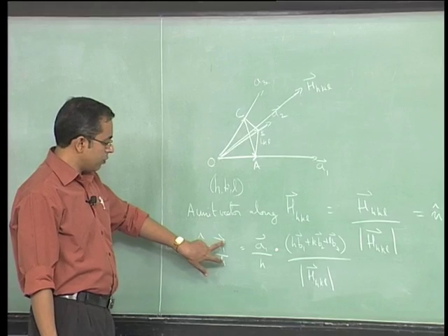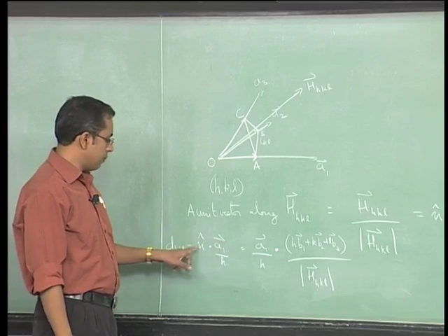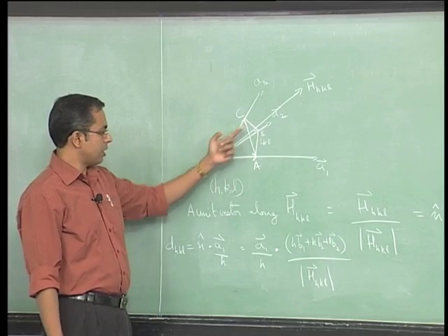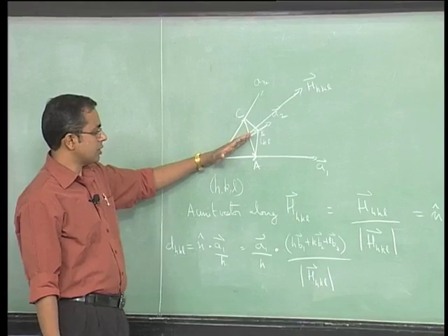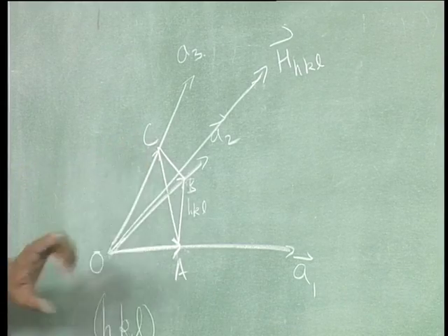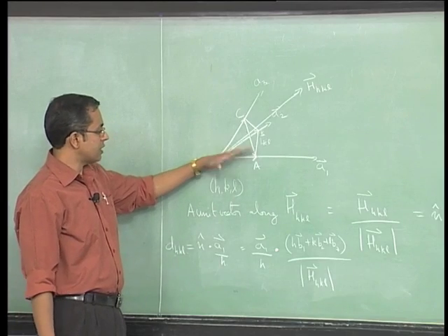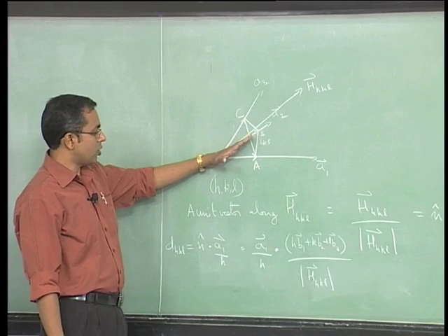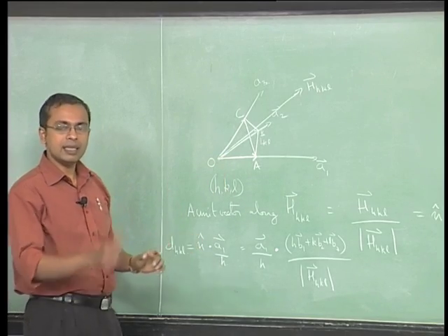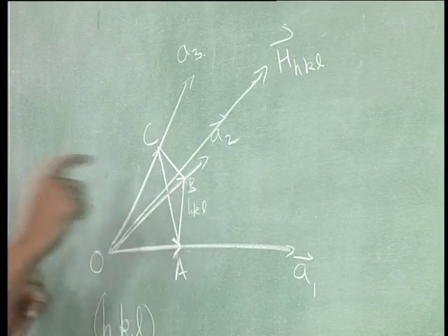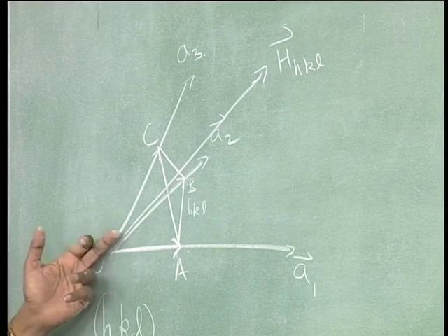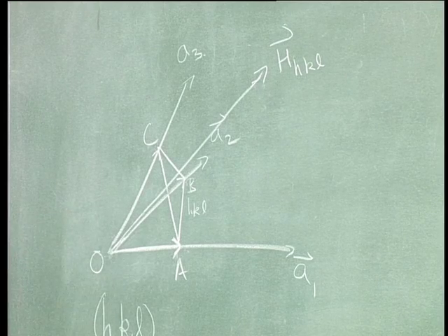the component of any of those intercepts along the perpendicular to that plane. So that perpendicular is now going through that origin. If you take the component of this vector along the direction of that perpendicular, you therefore get the distance in this direction. That unit vector is simply giving us the direction, but if you take the component of this intercept OA along that direction, or any of those OB or OC along that direction, that would then represent the closest spacing between the origin and that point, and at that point that vector will be perpendicular to that plane, which is how we have defined it.